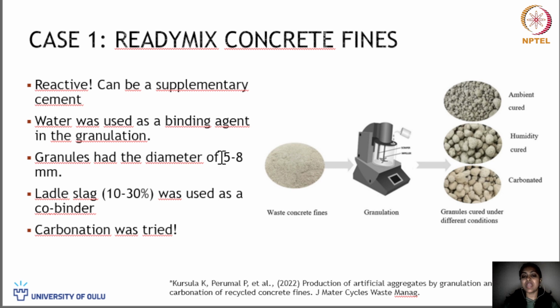The granules were made in a diameter of 5 to 8 mm. And ladle slag, which is a type of byproduct from the steel industry, has been added as co-binder. The idea is to improve the carbon capturing capacity of this material, because ladle slag had higher carbon capturing capacity compared to this ready mix concrete fines. So we tried carbonation in this study.